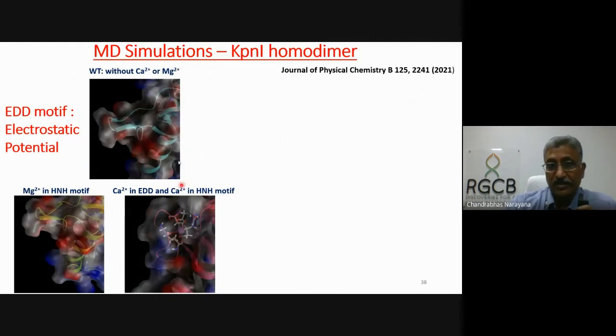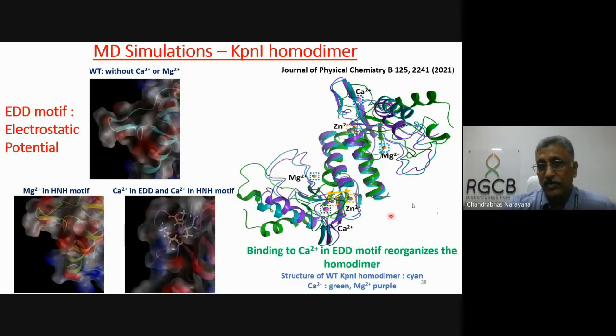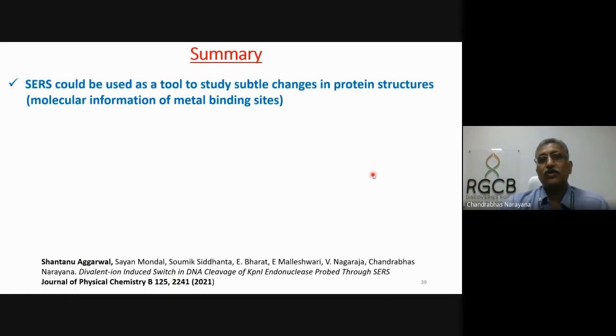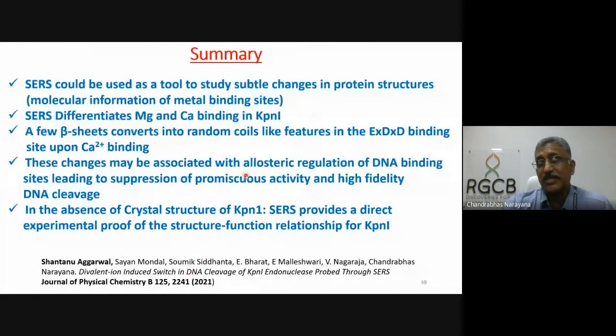And in fact, this is the homology model of that MD simulation. And you can superimpose the whole structure, and you can see the wild type, which is given by the cyan color. And green is the calcium bound, and magnesium is purple. And when we superimpose it, you can see the wild type and the magnesium do not change this beta sheets, but the calcium actually changes, and because of which there is a subtle variation in the tertiary structure of the protein. And that is the reason why this is able to do a non-promiscuous binding.